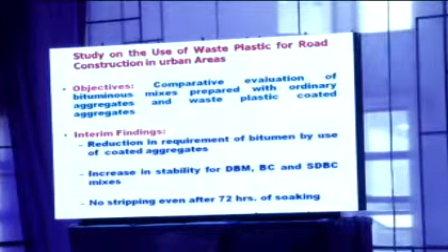Next is a study on the use of waste plastic for road construction in urban areas. Under this project, waste plastic coated aggregates have been used for the bituminous mixes, and it has been observed that when you use plastic coated aggregates, the binder requirement goes down, and we observe an increase in stability for all DBM, BC and SDBC mixes, and no stripping takes place even after 72 hours of water soaking.